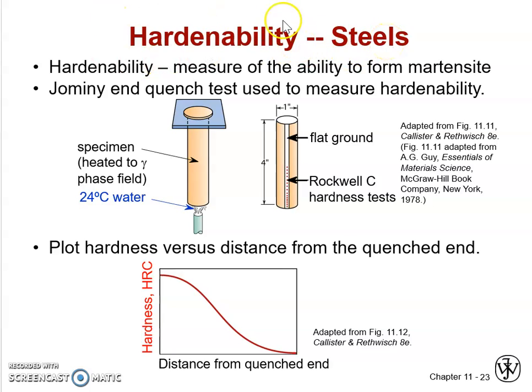So now, how to measure the hardenability of steels? So what is hardenability? It is a measure of the ability of the steel to form martensite. Okay, so you know that when the steel has a martensite structure, it has a very high hardness, right? So how to determine the hardenability? You have to do an experiment called the Jominy end quench test. Okay, it is used to measure hardenability. So what you will do is you put your specimen, which is the red one here, and you heat it to austenite temperature. Okay, austenite phase. And then you cool it by putting the water jet here, which is 24 degree water.